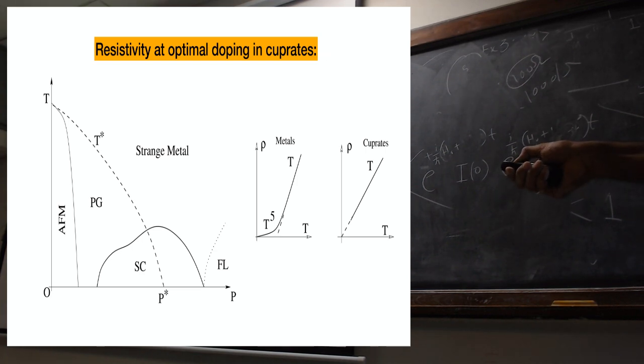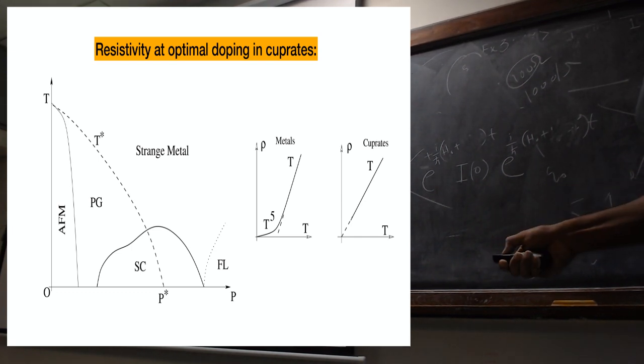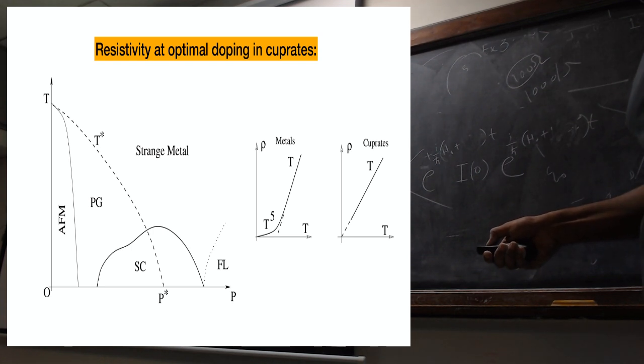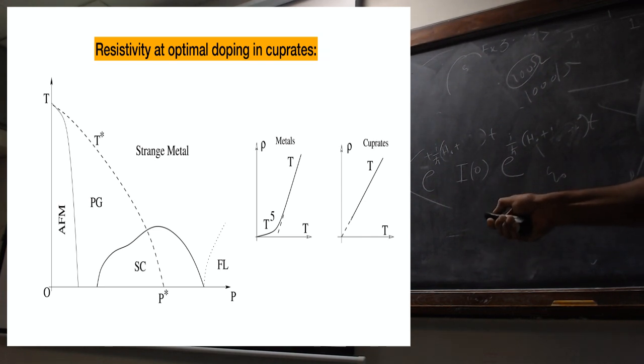Okay, so switching gears, this is the problem of cuprate superconductivity. Cuprates are notoriously difficult to understand. 35 years have gone by, and people don't understand the mechanism. At zero doping it is an antiferromagnet. When you start to dope, the antiferromagnet goes away and the superconductivity emerges. Exactly at this point P star, where the superconductivity is maximum, the resistivity becomes linear. It is linear in temperature.